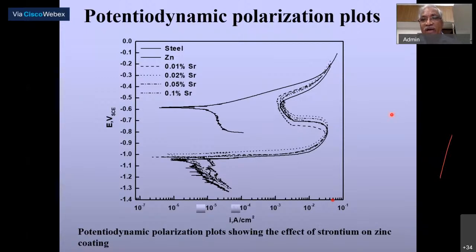When you are doing this, if you look at the Bard book, how to deal with the diffusion, it's a very interesting thing. When you are going to do this pulse, there is always a time lag between the current and the potential because of either over voltage or also diffusion control process. So you are going to complicate your current potential relationships, and you are not able to interpret what is going on in the surfaces at all, actually, right? Whereas in a steady state one, where you have DC, you have less of a problem. So the pulse things generally, in my view, is not done.